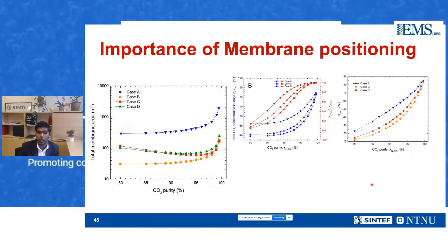Where does it change the membrane area as well? Yes, it does. And here we have a very interesting trend where, for example, for cases C and D, if you look at the trend of CO2 purity and the total membrane area required, it reduces and then increases. But then there is a place where there is a minimum, where the membrane area requirement is reduced to an extent where it's the lowest in that system.